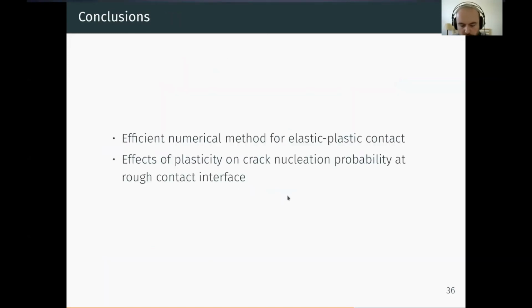So that's the end of the continuum part. I've showed you what I think is an efficient method for rough surface elastoplastic contact, and I've applied this method to trying to compute a macroscopic quantity, this crack nucleation likelihood, on a rough surface interface for adhesive wear.